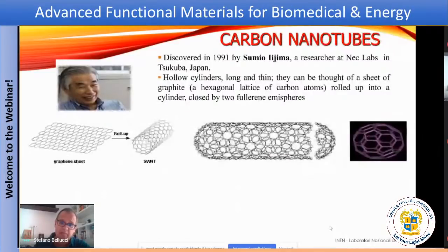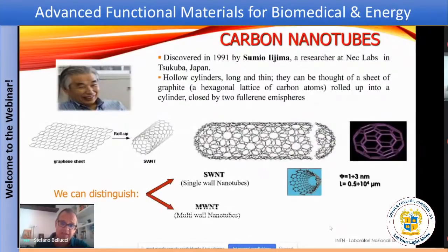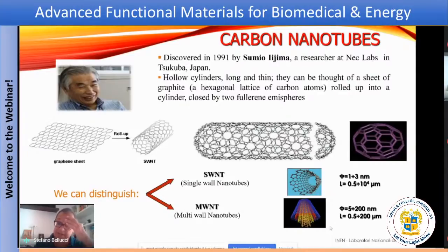As I said, they were discovered in the 1990s in Japan. They're hollow cylinders, long and thin. You can have 2 types, 1 layer, so-called single wall nanotubes, or multi-layer, multi-wall nanotubes. They have a tremendous aspect ratio. That means the ratio of the length of the tube divided by its diameter. They're practically quasi-unidimensional objects. The aspect ratio can get to the level of 10 to the 7 very easily.